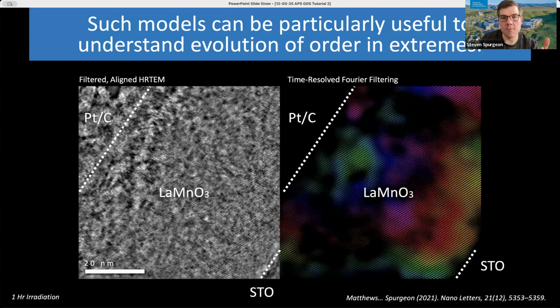What we're seeing is that microstructure evolving, it's beginning to break up. And on the right side here, we're looking at a Fourier filtering of that to measure crystallinity over time. Now, this really only captures one facet of how the material is responding to radiation. And so we can start to employ multimodal models to better understand not just materials microstructures and crystallinity, but also